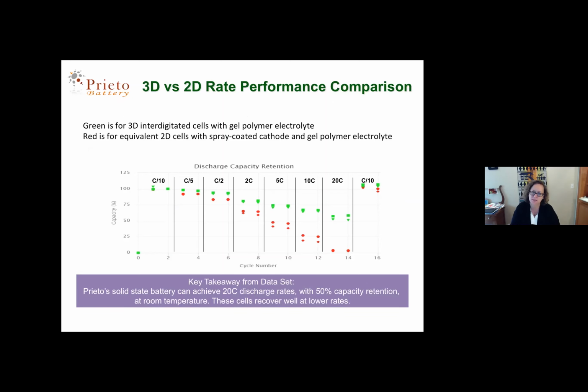And what you can see is by the time you get to 5C, 10C, 20C discharge rates, the 3D battery is retaining capacity significantly better than the 2D battery. But when you slow back down to C divided by 10, the capacity retentions recover. And so that's telling you that the chemistry of the materials is pretty robust. And the 2D battery does recover, but at high discharge rates, the conventional 2D architecture just can't keep up with the 3D architecture.